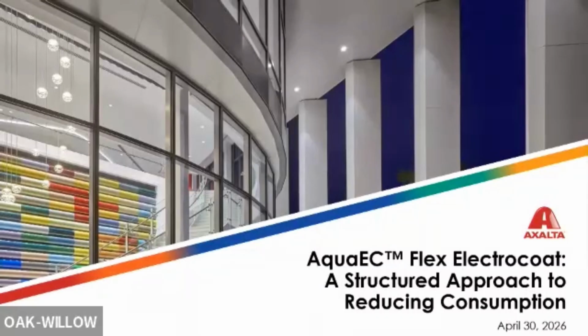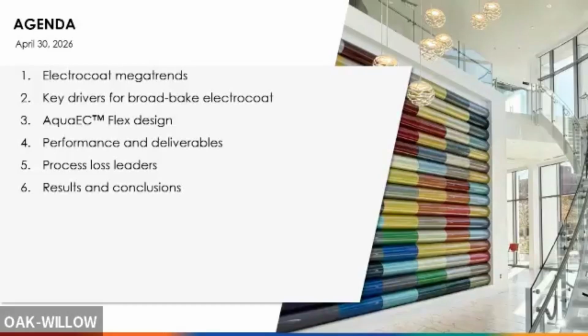It's the same technology. In short, it means basically maintaining all of our properties at the high level at 200 C bake. A standard Ecoat would cure at 160 C, right? 10 minutes, 20 minutes at 160 C. And then pushing our properties down into the 140 range, which is new territory for us, and still delivering all of the properties. So that's what we mean when we say standard bake, broad bake, and low bake. So I'm going to use those interchangeably.